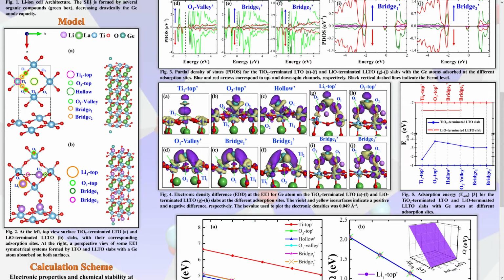Model. As can be seen in Figure 2a, on the lithium titanate surface with a titanium dioxide termination, germanium atoms were placed at different absorption types, labeled as titanium top, oxygen top, hollow, oxygen valley, bridge 1 and bridge 2. Likewise, on the surface with a lithium oxide termination, germanium atoms were placed in the lithium top, oxygen top, bridge 1 and bridge 2 absorption types. Figure 2d.